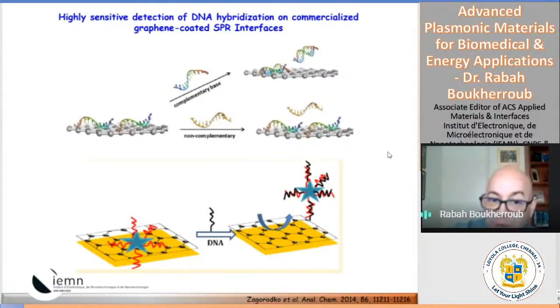Here I will just give examples of how we can use this. We use it for DNA hybridization. It's simple because single-stranded DNA will adsorb very nicely on graphene. Without anything, you just put it, it adsorbs because you have this pi-pi stacking and hydrophobic interaction. However, if I now bring the complementary DNA strand, it will hybridize with the DNA strand on the surface, and this hybridization will break the interactions of DNA with the graphene surface.